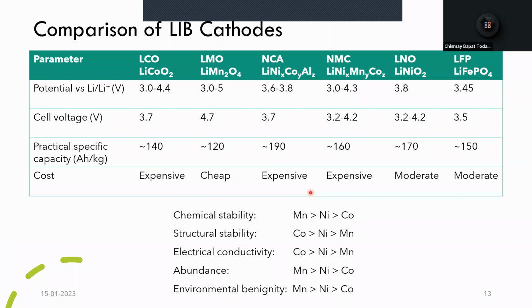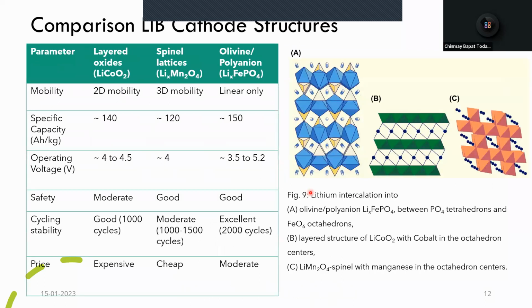Yes, sir. That is a really excellent question, and I think you really have some really good insights. So lithium dendrite formation occurs at the anode when the potential of the anode material is towards zero, and at the cathode when the potential is on the higher side. As I said here, the normal working potential for the cathode is around 4 volts, which is suitable for the current electrolyte that is being used, that is LiPF6. If you increase the potential further towards 5, then we have a chance of electrolyte decomposition on the cathode, and similar to SEI on the anode, we have a CEI, that is cathode electrolyte interface, on the cathode.